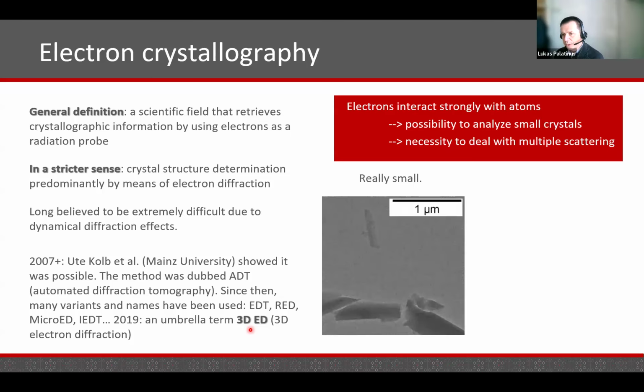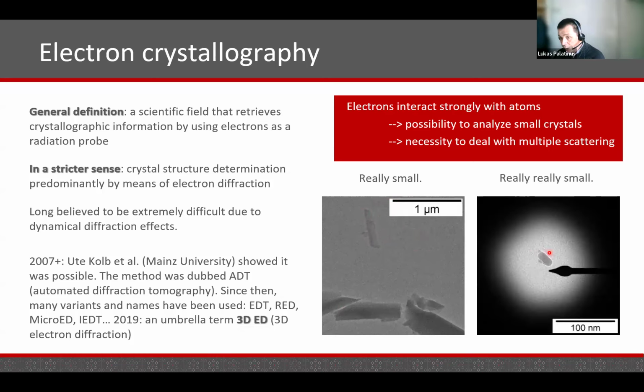But when I say we can deal with small crystals, that means really small. For a crystallographer, really small crystals, like, for example, here, this crystal has maybe about 100 nanometers in the smaller dimension. And this is a perfectly well-sized crystal for 3D ED investigation. But we can actually go down even more. This is a crystal which has just a little bit more than 10 nanometers in this shorter dimension, and it was still used to collect complete three-dimensional single crystal diffraction data.